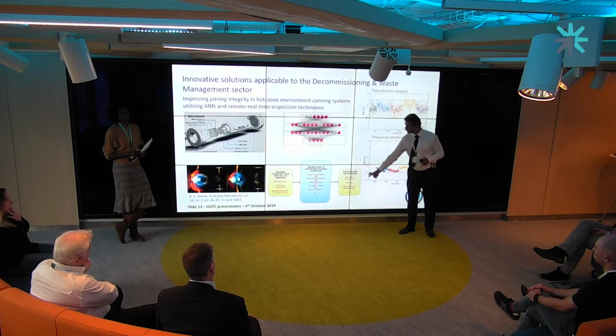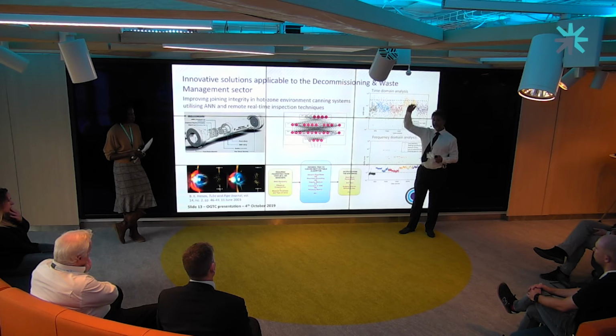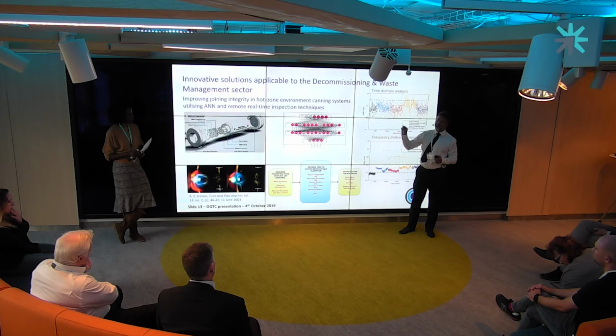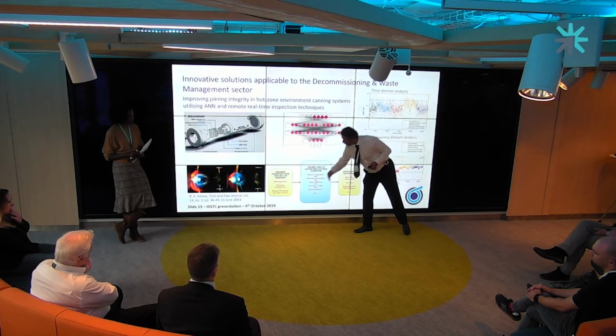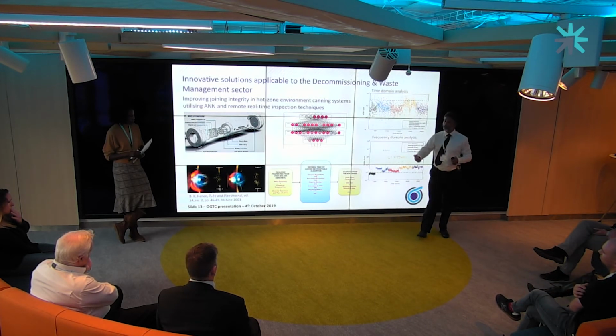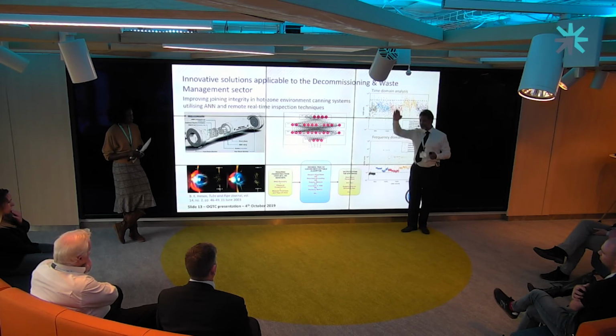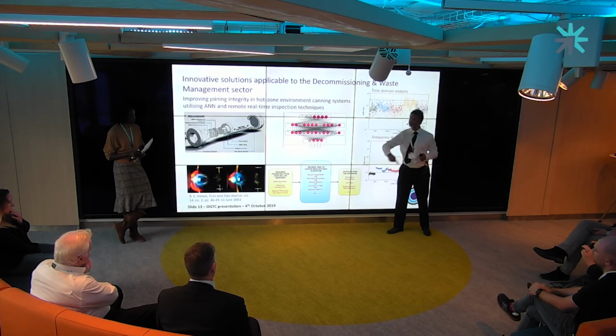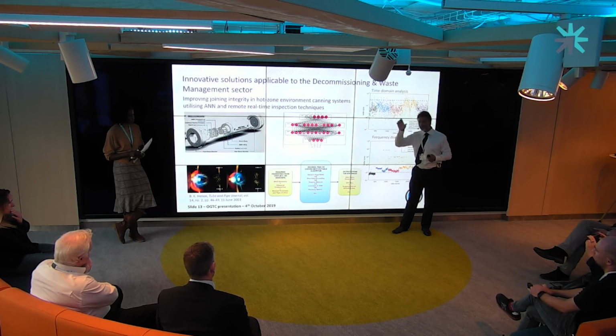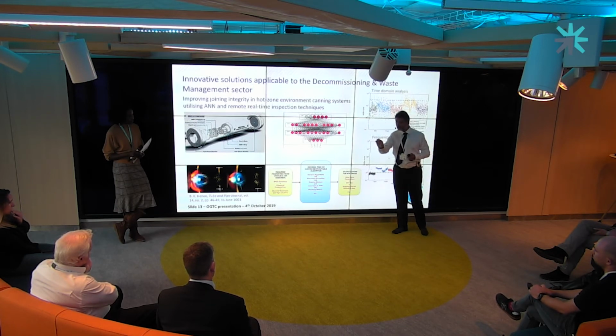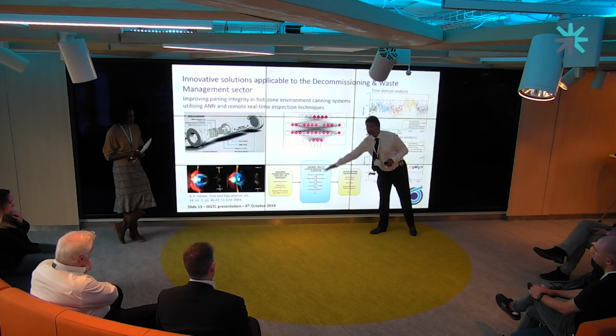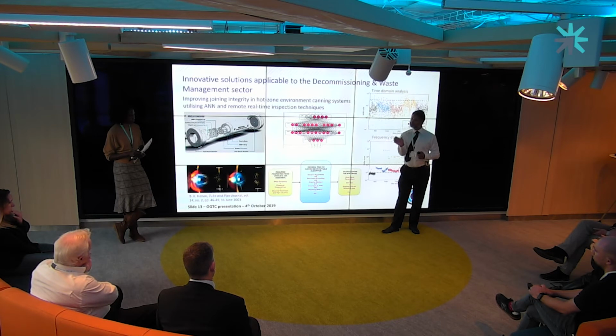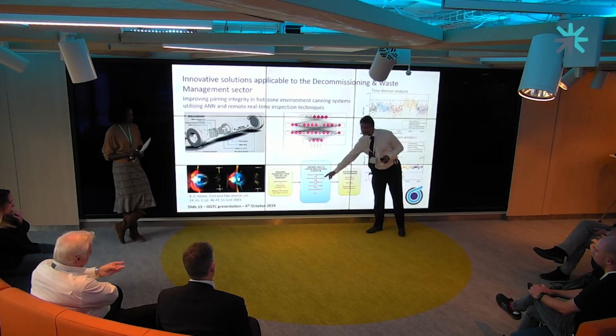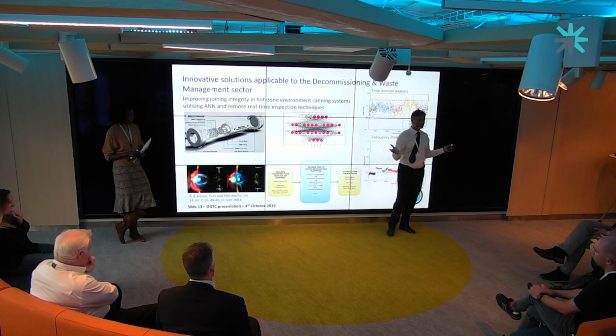So this was developed basically along the lines of, okay, how many critical parameters would be required to generate a prescriptive and a predictive term? So what happens here is you'll get artificial neural networks using back propagation. So you've got your weights, you've got your activation functions, you've got your feeders, and then you back propagate, iterate, etc., until you get an error function that's acceptable to you. However, the problem with that is it'll only tell you where the error is and whether or not you're going to be within standard. The use of genetic algorithms allows us to mutate that, hence the term genetic.